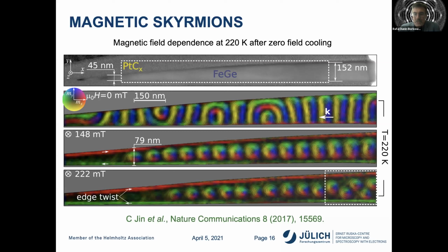And then in the presence of a stronger applied field, in the image at the bottom, the skyrmions start to form a zigzag array. And all of this can be imaged in real space with nanometer spatial resolution. The reason I show this is that these are really three-dimensional magnetic states, and we would ideally like to be able to image the three-dimensional magnetic structures directly.